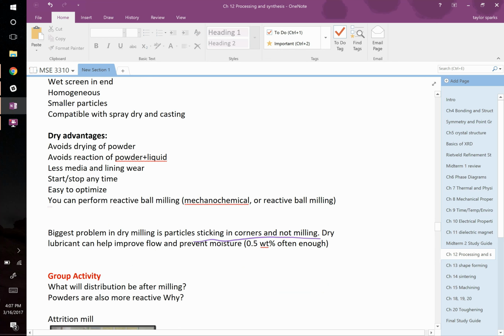Maybe you've got 2 or 3 different materials, and one is much more ductile and the other is much more brittle. And so they're going to wear and react at different rates, and some are going to get smaller than the others, because your ductile phase might just clump together in this milling process rather than break up into small pieces like you'd be liking.